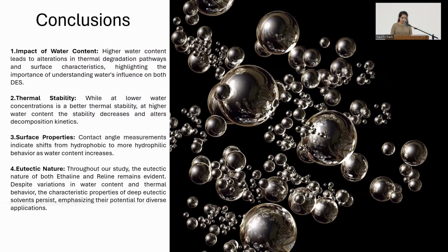Conclusion: higher water content leads to alteration in thermal degradation pathway and surface characteristics, highlighting the importance of understanding water's influence on both deep eutectic solvents. While at lower water concentration there is better thermal stability, at higher water content the stability decreases and alters decomposition kinetics. Contact angle measurements indicate a shift from hydrophobic to more hydrophilic behavior as water content increases.